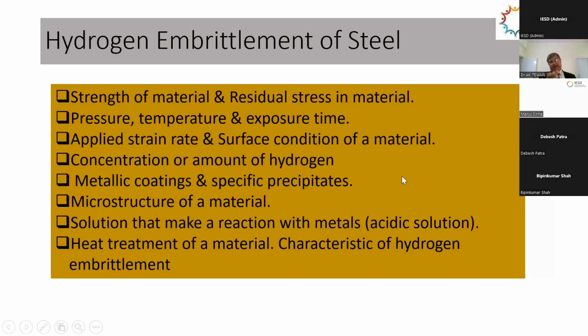I'm explaining because if you see the scanning picture of any metal, what hydrogen tries to do is go to the grain boundaries, inclusions, voids and dislocations, because metal appears very plain from the top. But under the microscope, there are hills and valleys, irregularities in the metal. The smaller hydrogen atom tries to settle there. That depends on the partial pressure of hydrogen, the total overall pressure, the concentration of hydrogen, and the temperature. That basically decides whether embrittlement, the passing of hydrogen atoms through the lattice of the metal, will take place or not. Accordingly, the controls are exercised in the pipeline.